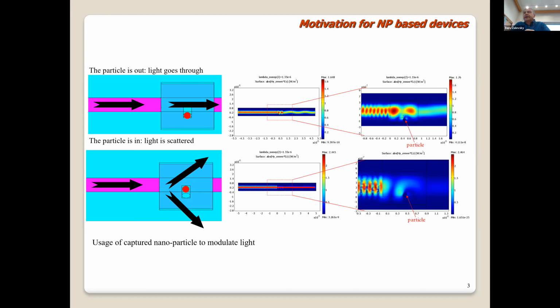So as I said, it is possible to realize dynamic devices in silicon. One way of doing it is integrating nanoparticles into specially designed photonic devices. Let us assume that we have a device that is seen in this slide, in which we have a waveguide that guides photons. And then on the path of this waveguide, we generate a nanometric hole in which we place a charged metallic nanoparticle. Now, this charged metallic nanoparticle, when it is positioned in the lower part of this drilled hole, will not significantly affect the propagation, the guiding of the photonic radiation, as you can see in this simulation. So the radiation will be coupled to the output of this device.